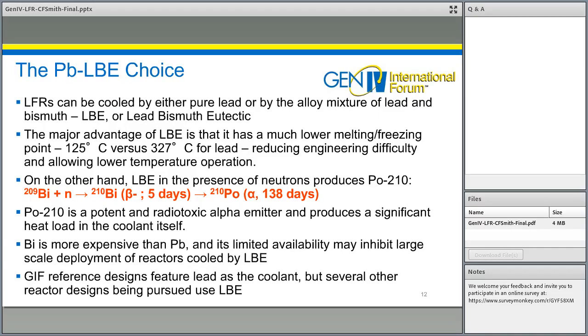Having mentioned LBE, let me say a few words about the lead versus LBE choice. First, lead-cooled fast reactors can be cooled by either pure lead or by the alloy mixture of lead and bismuth, LBE, or lead bismuth eutectic. LBE is the alloy of these two elements, lead and bismuth, with a composition that's approximately 55% bismuth and 45% lead. The major advantage of LBE over lead is that it has a much lower melting or freezing point, 125 degrees centigrade for lead bismuth, versus 327 degrees centigrade for lead. And this reduces the engineering difficulties and allows lower temperature operation. And those are the major advantages.